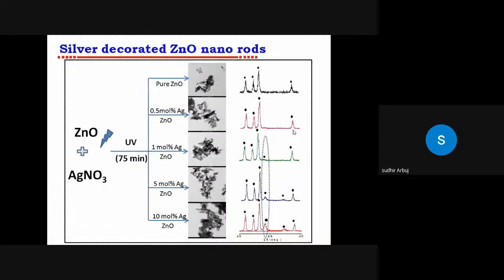Further, as I mentioned, the loading of noble metals or transition metals on the surface of zinc oxide increases the photocatalytic activity. In this regard, we prepared pure zinc oxide nanorods. On that, we loaded 0.5 to 10 mole % silver. This is the XRD pattern. Here, after 1 mole %, we are getting peaks for metallic silver nanomaterial. So X-ray clearly indicates the presence of silver along with the zinc oxide nanostructure.